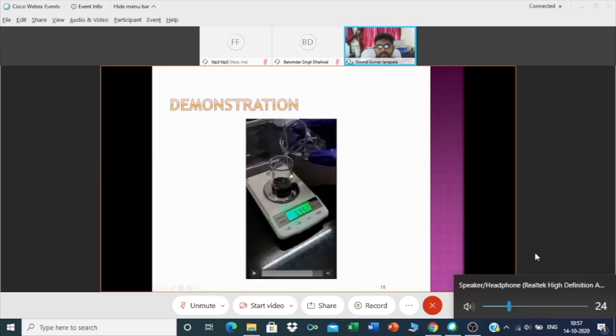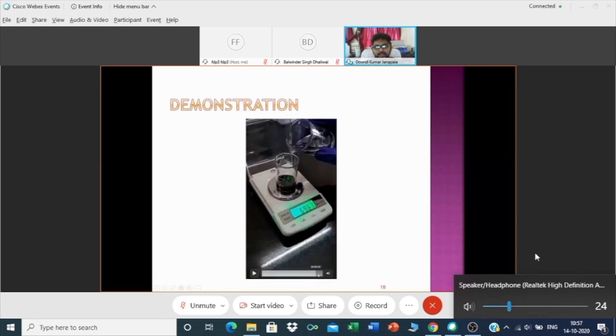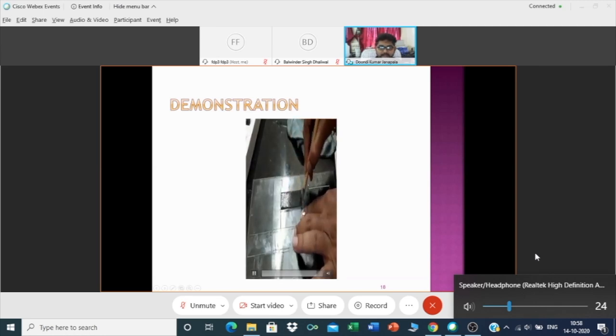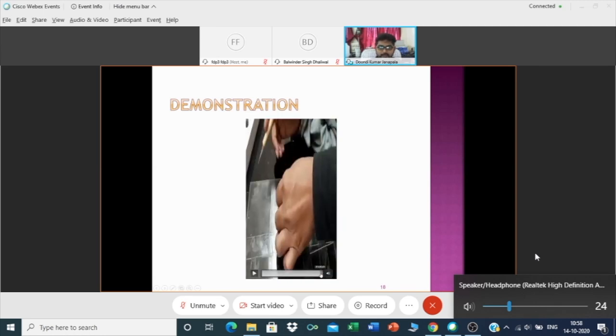What you have to do is, again, use the chemistry that I showed you. You have to mix it and put it in the sonication for 1 to 2 hours, so that the particles are mixed well into your PDMS uniformly, and then you pour it into the mold, just as I showed you previously, because I already showed you, right? I wanted to reduce the time, so I directly put that. So I baked it, and this is how you remove your polymer.